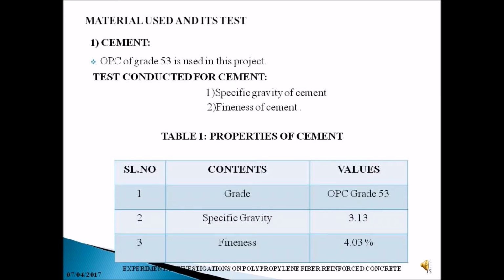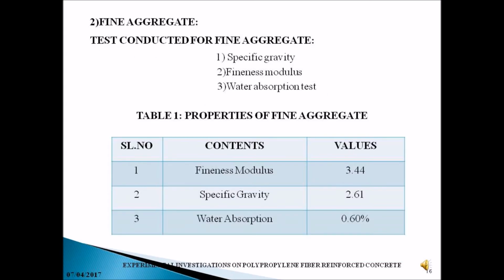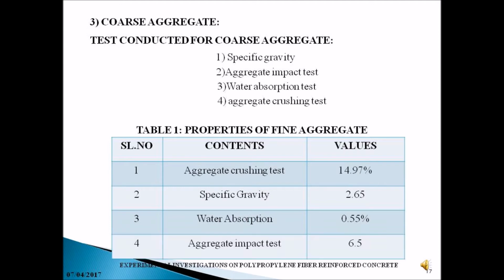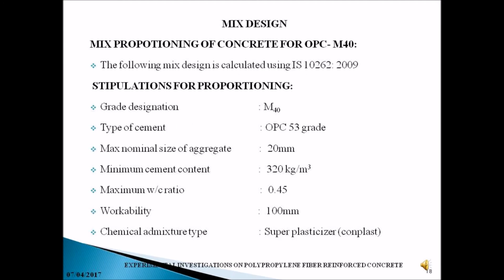Tests conducted for cement are specific gravity by Le Chatelier's apparatus and fineness of cement. These are the corresponding values. Tests conducted for fine aggregate are the same: specific gravity, fineness modulus, and then water absorption. The values are here. Tests conducted for coarse aggregate are specific gravity, aggregate impact, crushing test, and water absorption. These are the mix design.